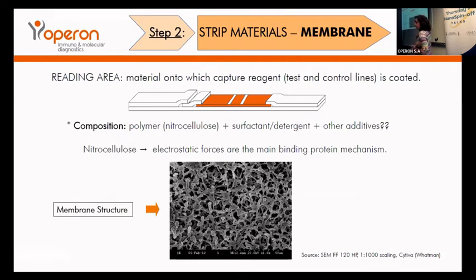Now the membrane. The membrane is one of the most important elements in lateral flow assays because here is the reading area. It is the place where we coat the capture reagents and immobilize them. It is mainly composed of a polymer that is usually treated with surfactants and detergents to make it more hydrophilic, and in lateral flow assays we usually use nitrocellulose membrane. The nature of the polymer determines the forces that bind the protein. In the case of nitrocellulose, these are electrostatic forces. Here you can see the structure of the nitrocellulose fiber in a microscopy view.